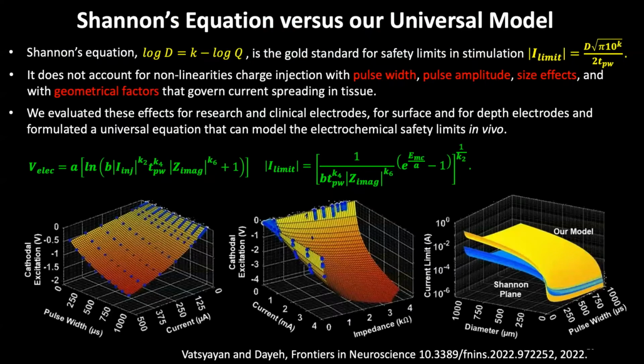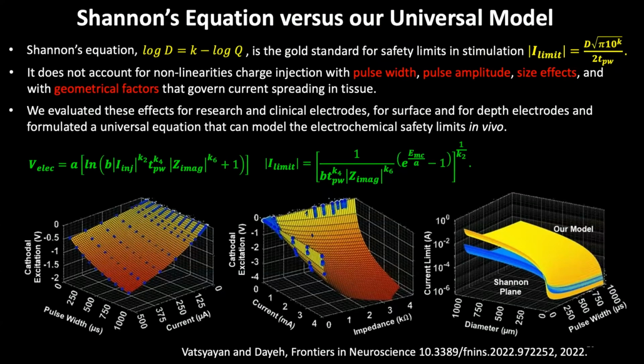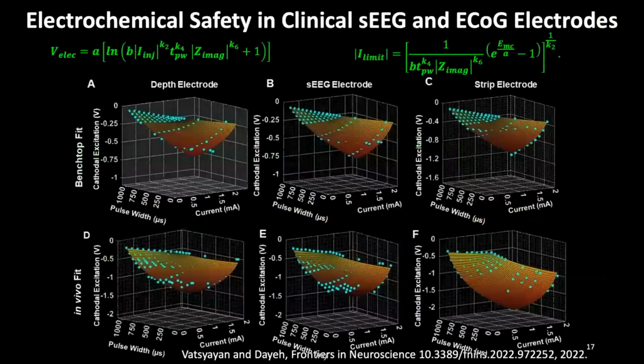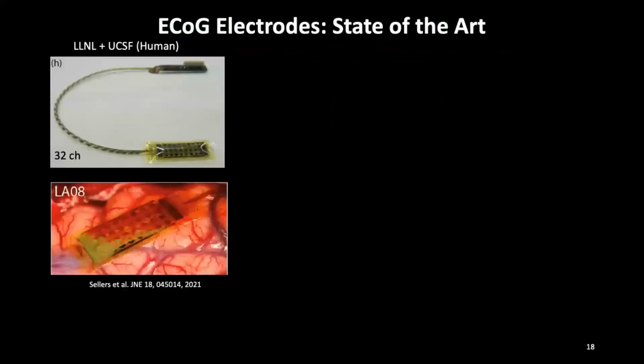adverse effects. And this shows basically how the model takes into account the nonlinearities, as I mentioned, in terms of pulse width, also the impedance of the device. So the material also is taken into account in this model, and the data that we measured fits very well with the model. And we've also applied it to clinical electrodes. On top, we're looking at fits for the voltage as a function of pulse width or current in benchtop and bottom in vivo. And the model fits also the data from clinical electrodes. So if you're interested, please take a look at this paper in Frontiers in Neuroscience that was published recently.